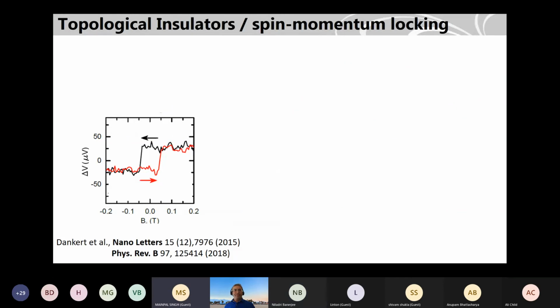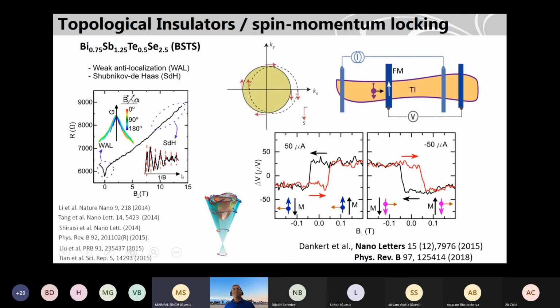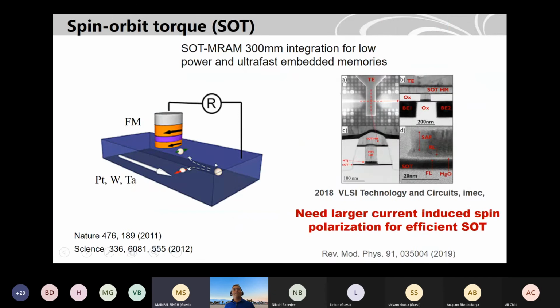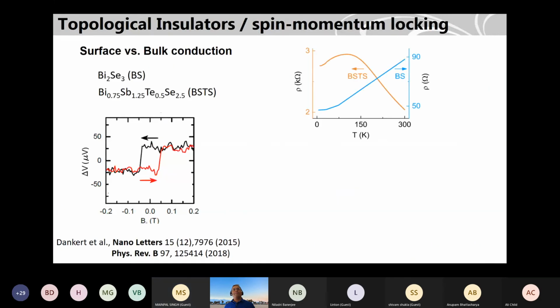Hello, sir. I was asking about that BSTS resistivity curve. You said that above a certain temperature, the bulk states are responsible for conduction, and below that temperature, the edge states appear. The question is, when we change the doping concentration, does the temperature change at which we get the bump, or below which the surface states or edge states dominate the conduction? So your question is whether, if we change the composition of this BSTS, this will change. Yes, that should happen.